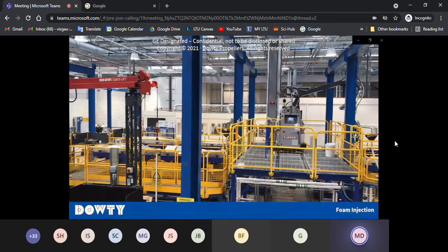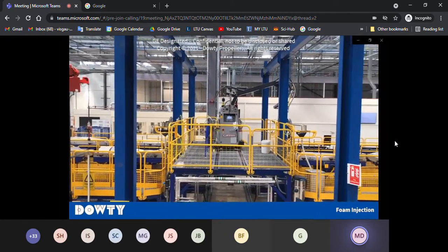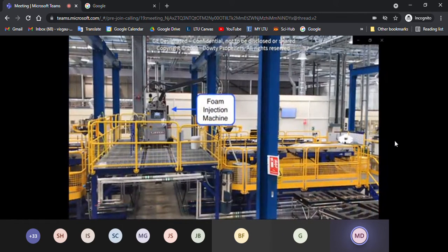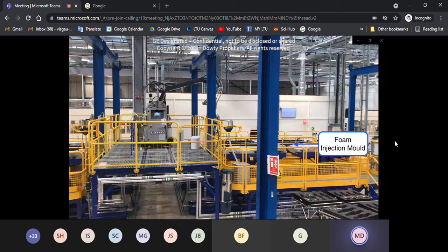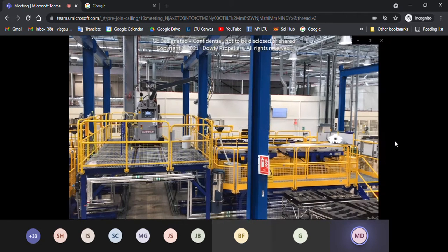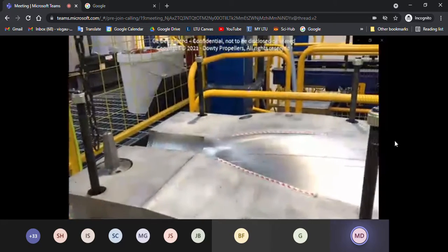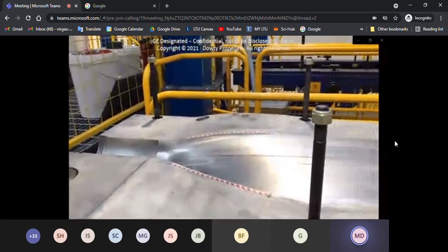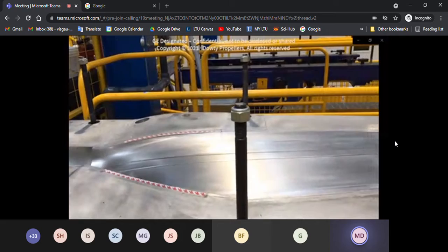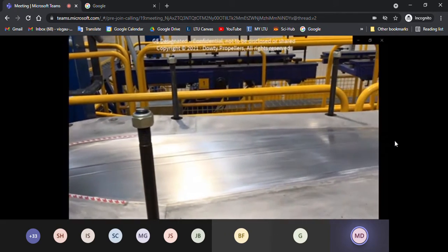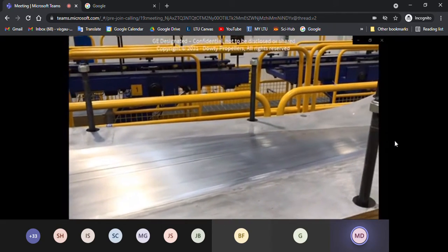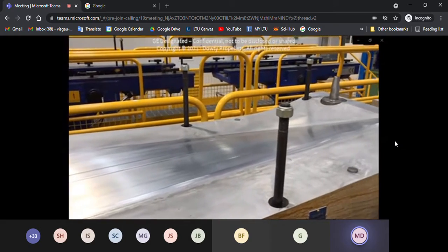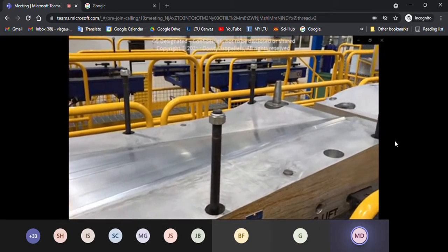And now you can see into the foam injection cell. So we have one central foam injection machine mounted on a sled. And off to the left and the right, you have multiple foam injection stations, each equipped with a foam injection mold. Here we have a close-up view of one of the foam injection molds. So we're looking at one face here, so both faces are open flat, and into each face we apply one dry carbon fiber preform for each face of the blade.